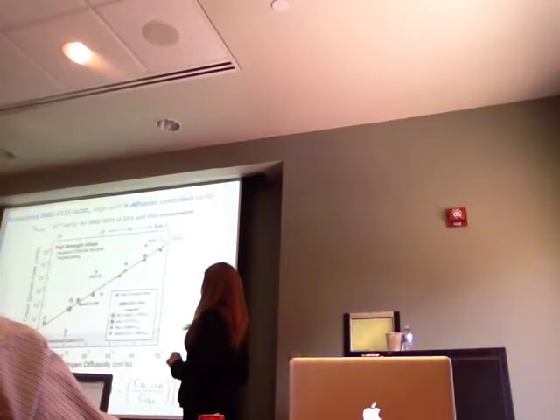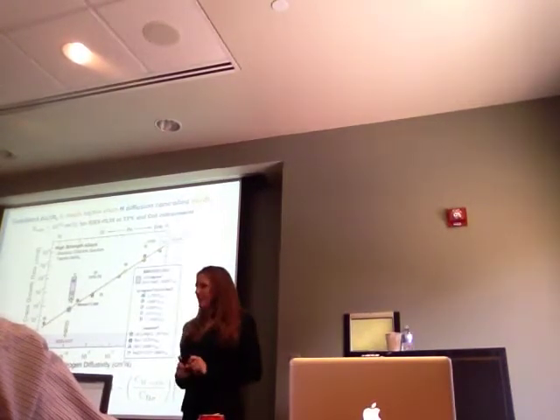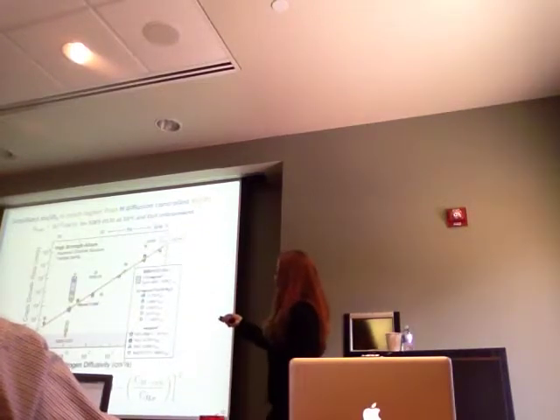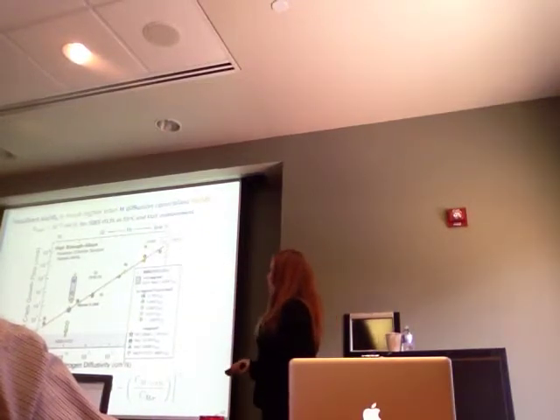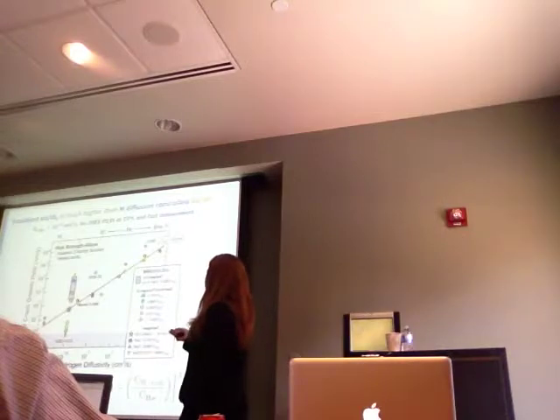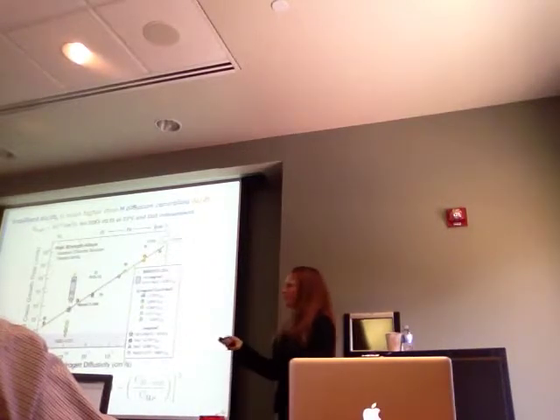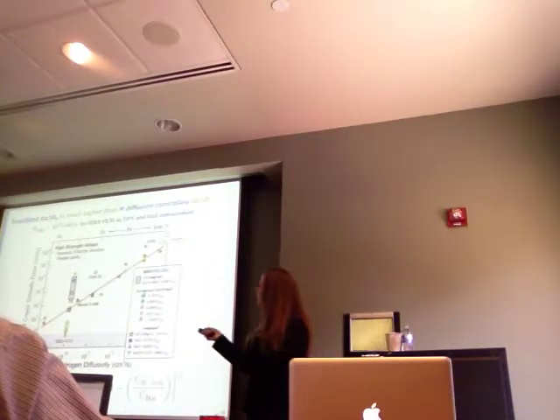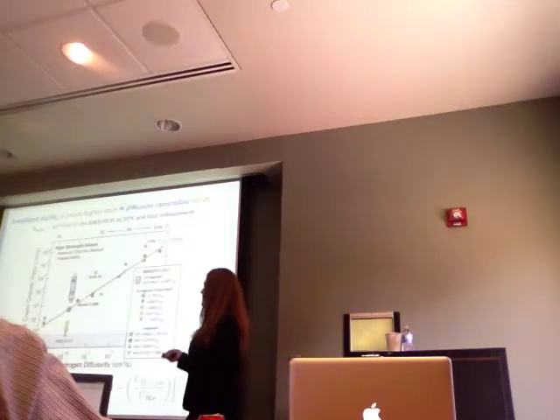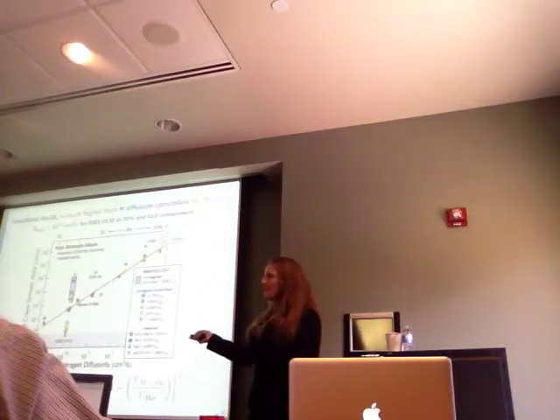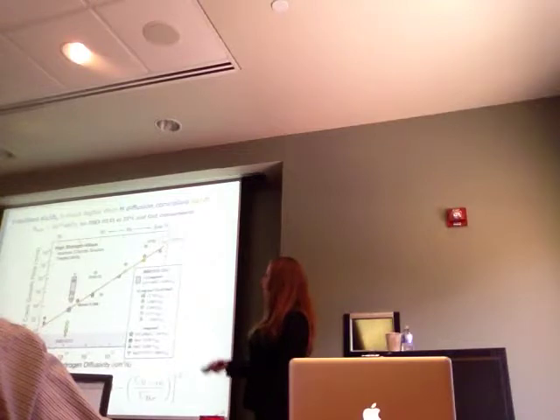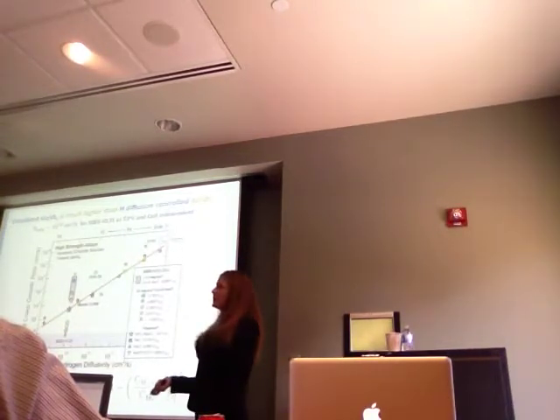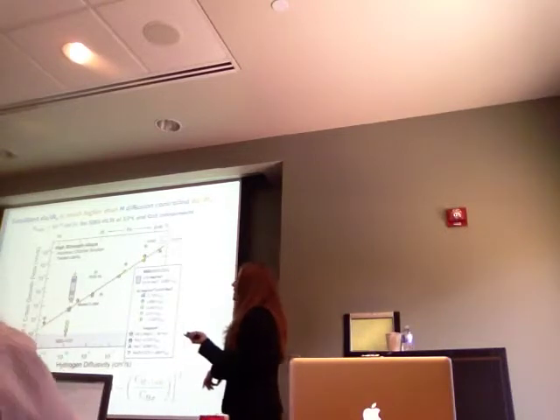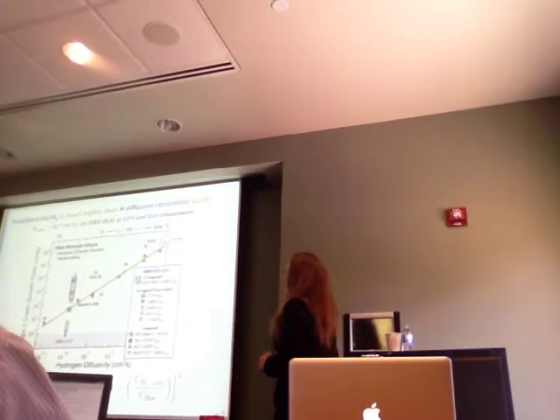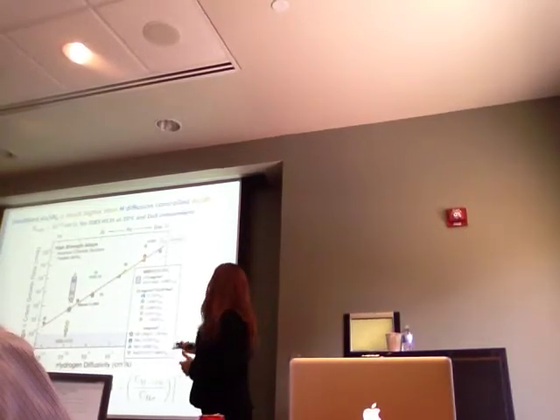Now the problem comes when we plot our sensitized data. All of the data at near open circuit potential in sodium chloride is the gray square, and that's well above this trend line. And then all of the polarization data is in these circles. You can see the anodically polarized data is above the line, and all the cathodically polarized data is below the line. And again, we can use this model to explain the data below the line, but we can't necessarily use that for above the line.